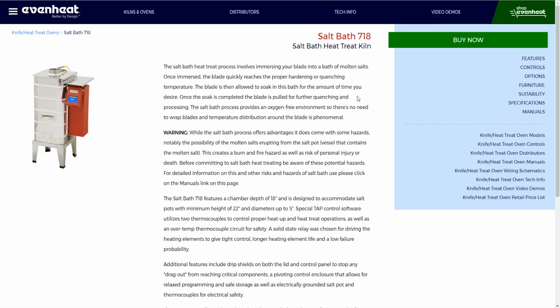The salt bath process provides an oxygen-free environment, so there's no need to wrap the blades, and temperature distribution around the blades is phenomenal. What they mean by wrap the blades is put the blades in something so they don't decarb. While the salt bath process offers advantages, it does come with some hazards, notably the possibility of the molten salts erupting from the salt pot vessel that contains the molten salt. This creates a burn and fire hazard, as well as risk of personal injury or death.